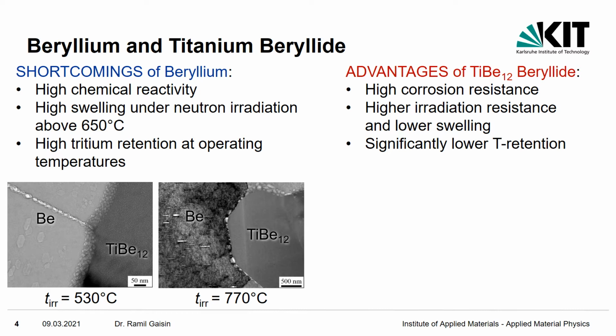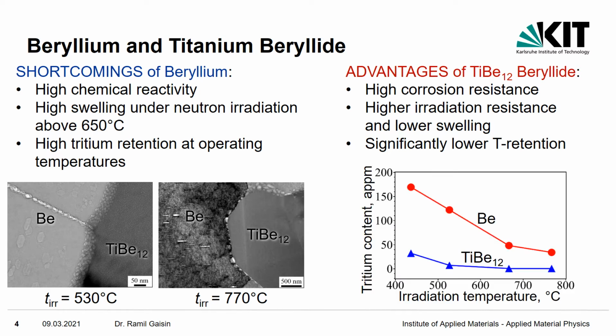Looking much closer to the material with TEM, we always see large hexagonal bubbles in beryllium and only very small ones in beryllide. This also leads to significantly lower tritium retention in beryllide, which is important from a safety point of view, since tritium is a radioactive element. All these advantages of titanium beryllide allow it to change the blanket design. I will show you this in the next slide.